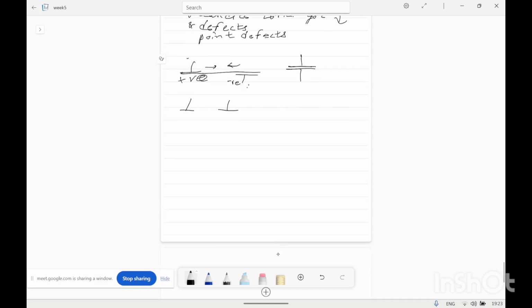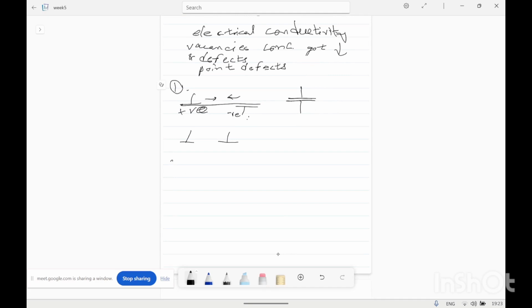So what happens if dislocations of the same sign come together? Next is polygonization. No, polygonization will come later. The same sign dislocations arrange in an array, in a vertical array, forming low energy grain boundaries, low angle grain boundaries. These are generally called tilt boundaries.